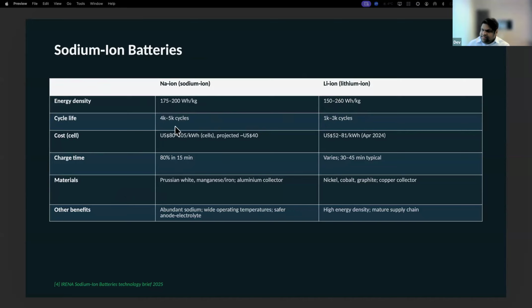However, you can see the charging cycles is much higher compared to lithium ion, around 4,000 to 5,000 cycles. And most importantly, the cost of the sodium ion is projected to be much lower than lithium ion in the near future, as soon as the economies of scale hit in. Another important breakthrough in the sodium ion technology is the charging time. It is much lower than the lithium ion. Around 80% of the battery gets charged within 15 minutes.